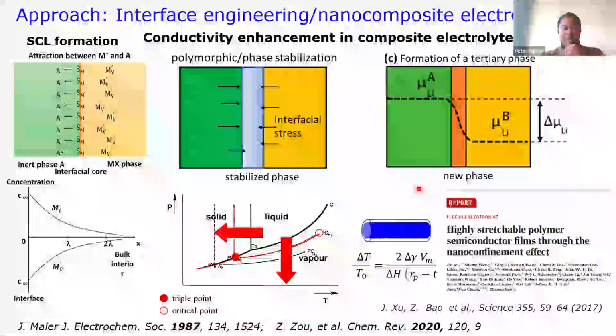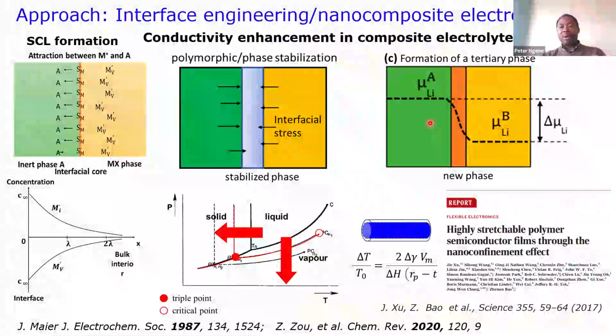How do we change the ionic conduction behavior? So why do we want to do that? If you make a composite, there are three things that can happen. We can have interaction at the interface, leading to what we call space charge formation, a space charge layer, which can enhance the different concentration at the interface, thereby leading to high ionic conductivity. You can see here the different concentration.